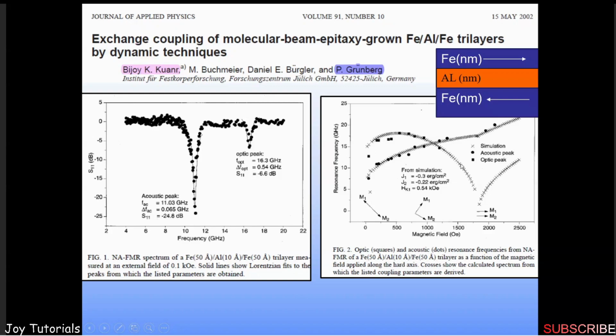Through the theoretical fitting, one can find out what is the exchange coupling between the two iron layers through the aluminum layer, depending upon the thickness of the aluminum layer and also the magnetic field. So you have a decoupled side, you have an exchange coupled side, you have a 180-degree configuration of the two magnetizations, you have a 90-degree coupling where there is a crossover between the acoustic and the optic mode. Then you have a parallel coupling, and there's a decoupled mode in a parallel state.